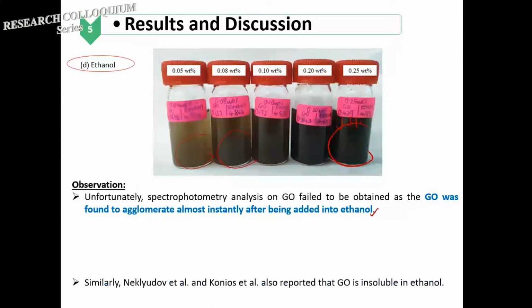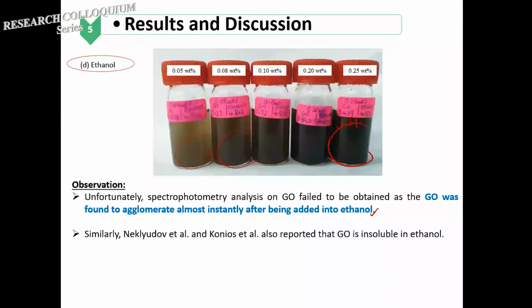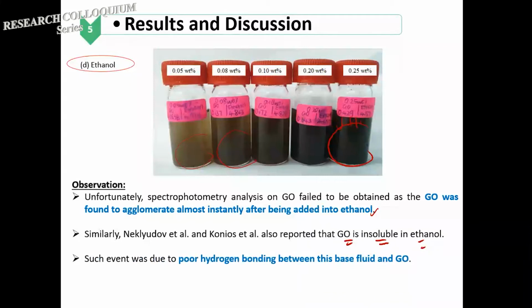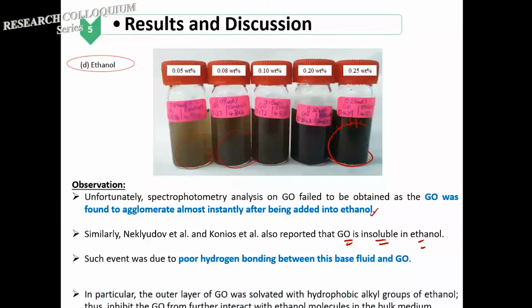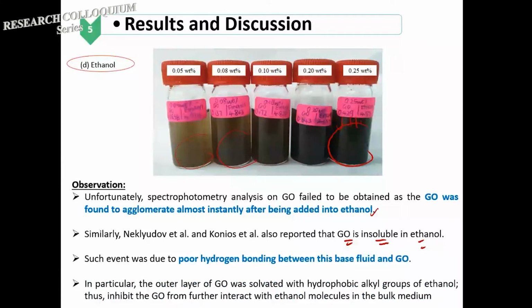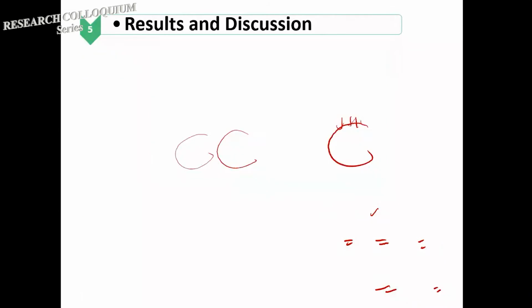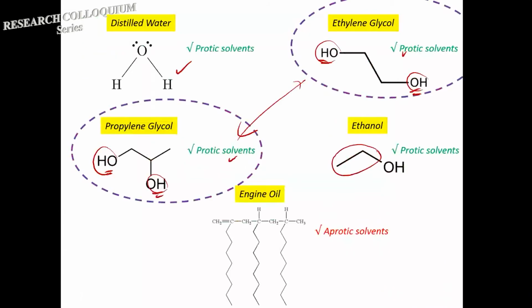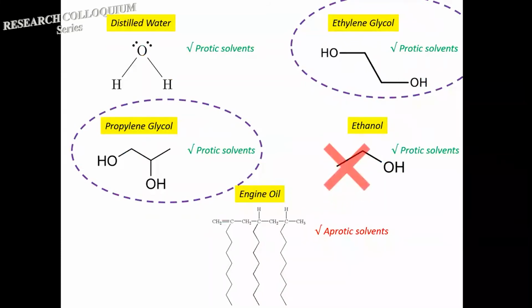Now, we investigated why this happened, and in fact, we noticed that there are two researchers that also found that graphene oxide is insoluble in ethanol. Now, this could be due to the poor hydrogen bonding between the ethanol and the graphene oxide. In particular, at the molecular structure level, it could be due to the outer layer of the graphene oxide, which is already covered by the hydrophobic alkyl group of the ethanol, making the graphene oxide not able to interact with the ethanol molecules in the bulk medium. It's mainly due to the alkyl group over here. Okay, making the graphene oxide no longer able to interact with more ethanol. In this case, we notice that ethanol is not a good heat transfer fluid when you mix it with the graphene oxide.